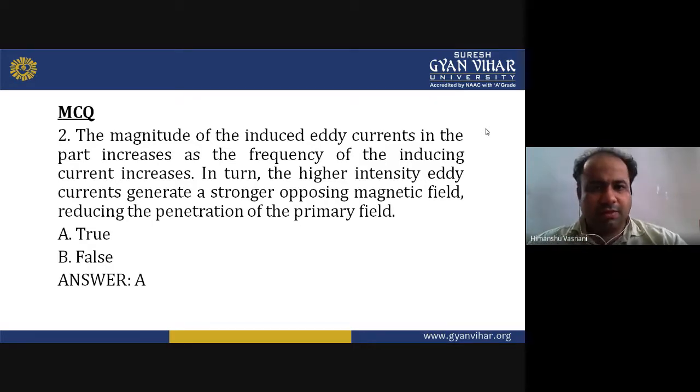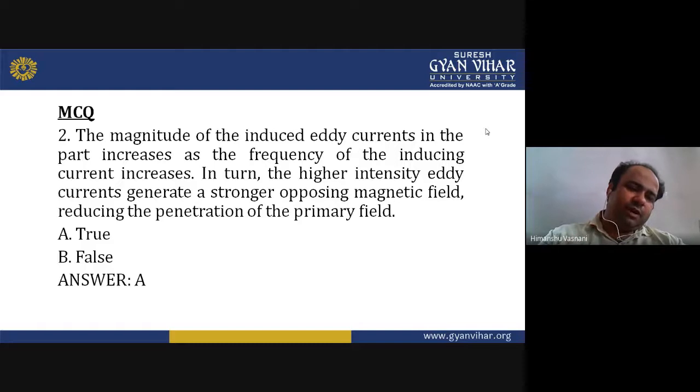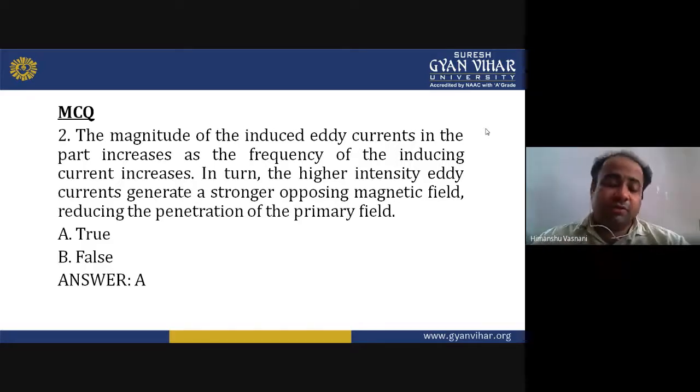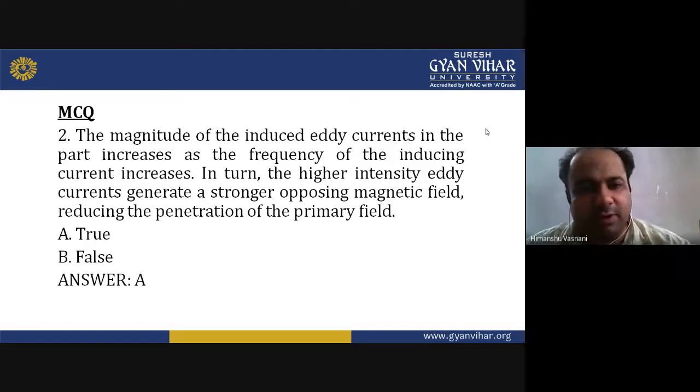Say that the magnitude of the induced eddy current in the part increases as the frequency of the inducing current increases. In turn, the higher intensity eddy currents generate a stronger opposing magnetic field, reducing the penetration of the primary field.